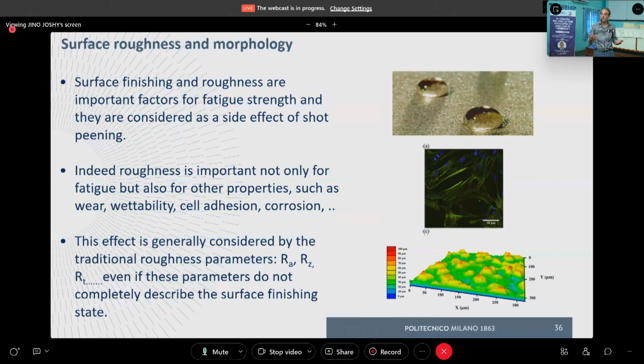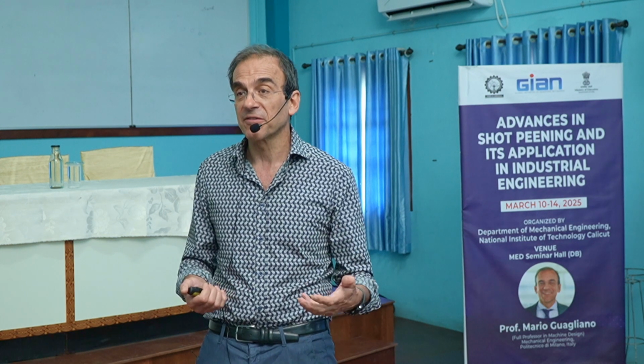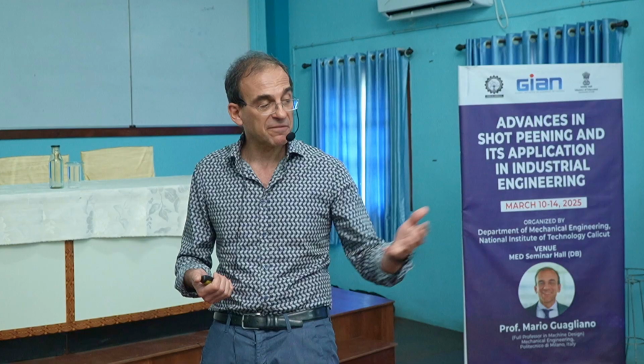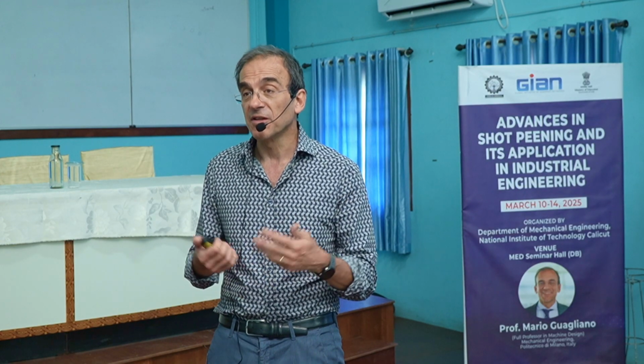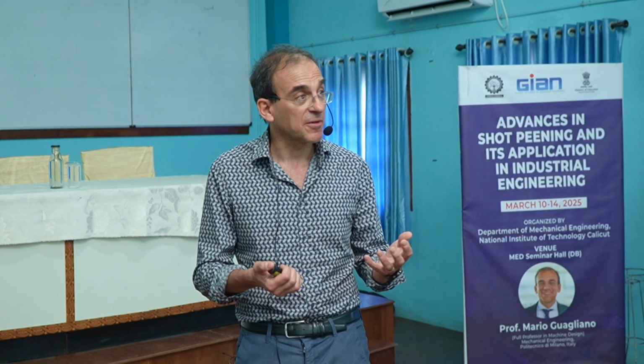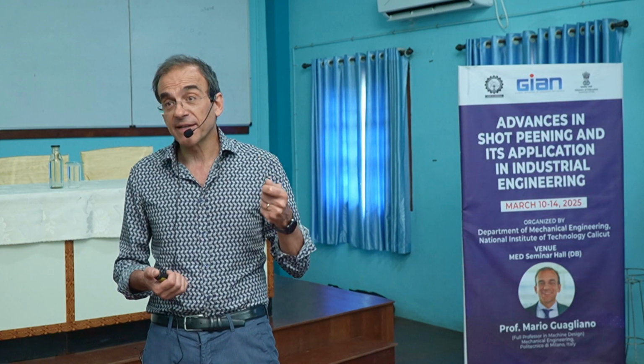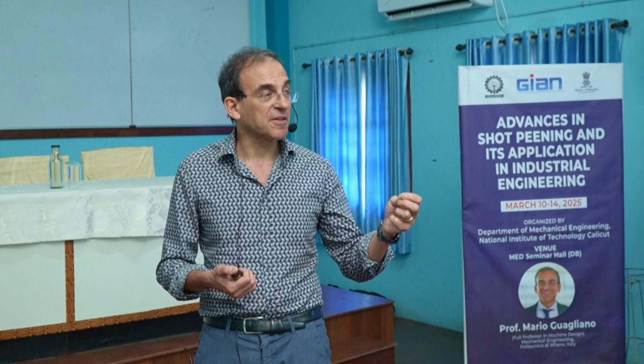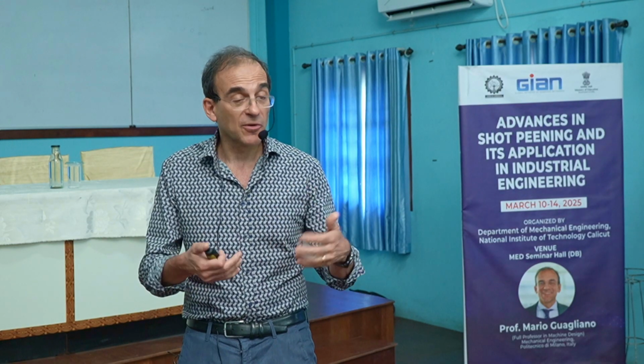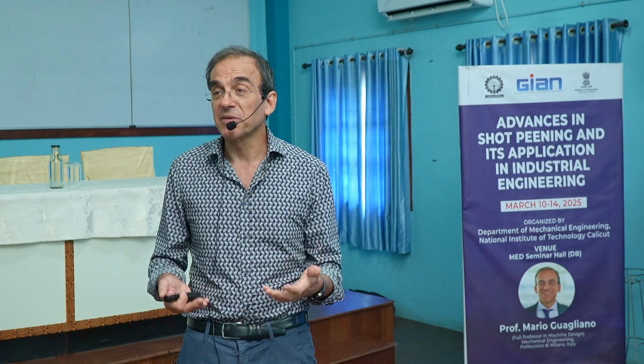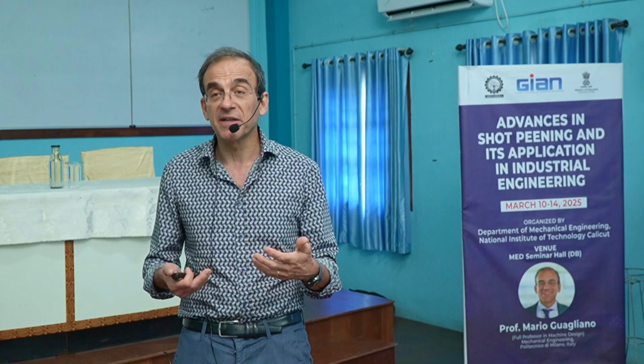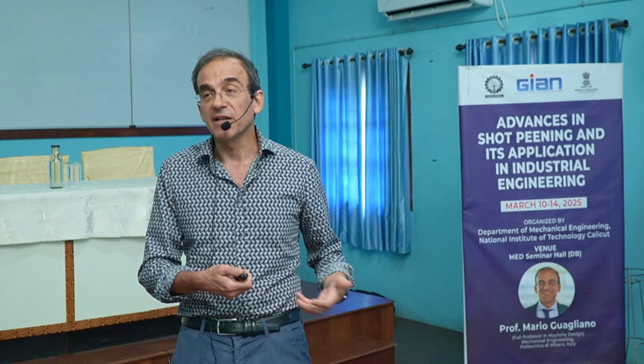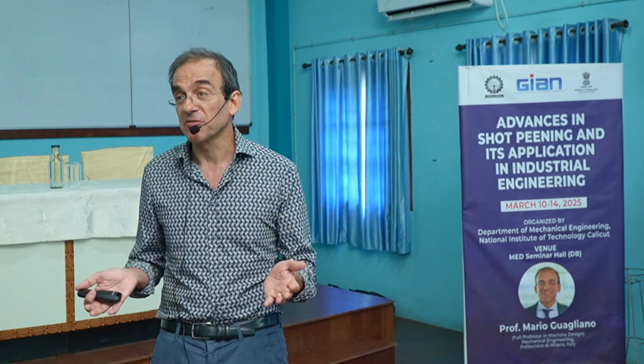When could cell adhesion be useful? Say in orthopedic prostheses. If we want to increase the osseointegration to reduce the probability of possible infection and so on, the roughness and texture of the prosthesis is important. And shot peening can be used for obtaining an effect like this. Without forgetting that, apart from this effect in terms of surface functionalization, we are still obtaining compressive residual stresses. And so we are obtaining a functional surface with an improved fatigue strength. And for a prosthesis, this is also important.